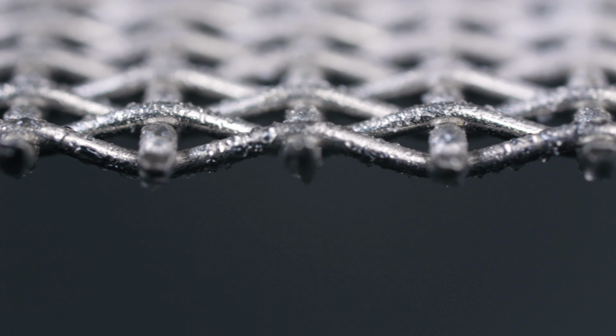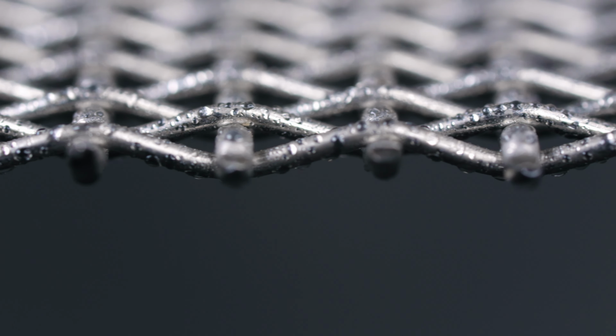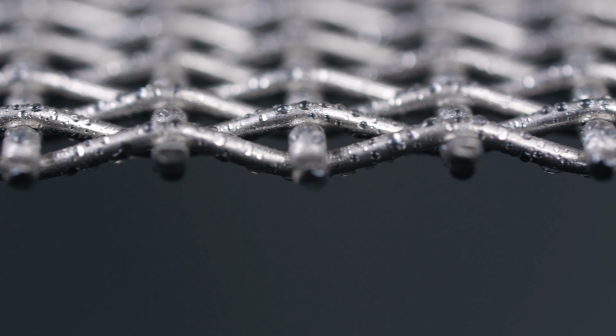Processes such as biomass combustion, industrial drying, and certain waste-to-energy operations typically fall within the 260 to 450 degrees Celsius range, 500 to 840 Fahrenheit. While these temperatures are more moderate compared to extreme applications, the contrast with the ambient air still poses a risk. Systems in this range must be designed to handle gradual heating and cooling cycles to prevent condensation and material fatigue. Filter media like glass fiber or intermediate-grade stainless steel mesh are commonly used here for their balance of thermal resistance and cost-effectiveness.